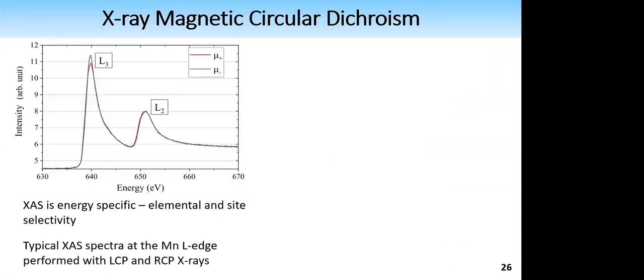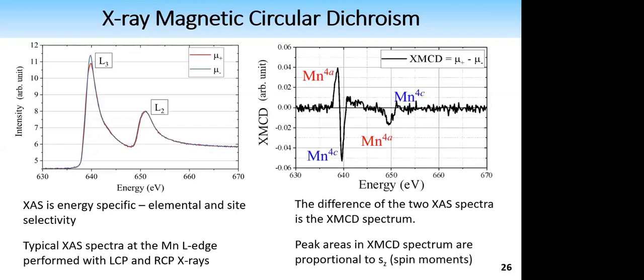So firstly, X-ray absorption spectroscopy measurements were performed with circularly polarized light at the L edge of manganese. Typical spectra are shown on the left. The two spectra are subtracted to obtain a dichroism spectrum, which I've now shown on the right. Sum rules are basically equations that are used to calculate spin and orbital moments. However, they require the integration of the entire spectrum, which would yield only the net moment.